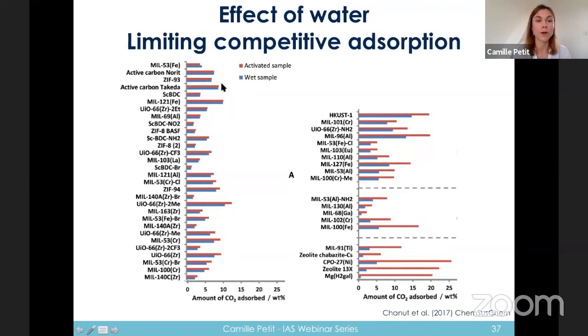That was done for a number of materials, many MOFs, and also some carbon and zeolite. And what you can see here is that for some materials, the water will not affect much the CO2 uptake. However, for others, especially the one here at the bottom, you'll have a dramatic decrease in the uptake. And so that is something that, of course, needs to be taken into account. If we think about CO2 capture, water is present in non-negligible quantities. That will be important.